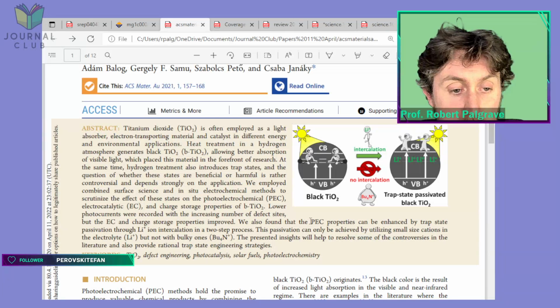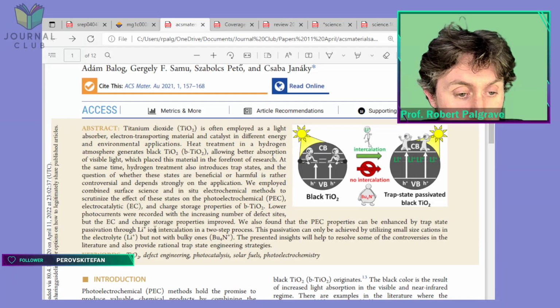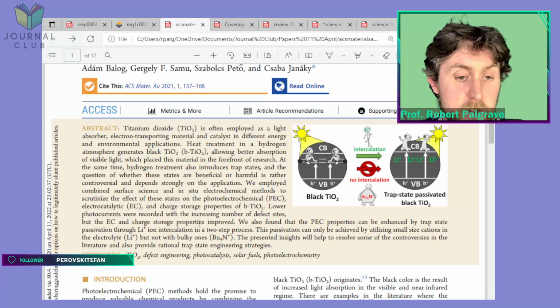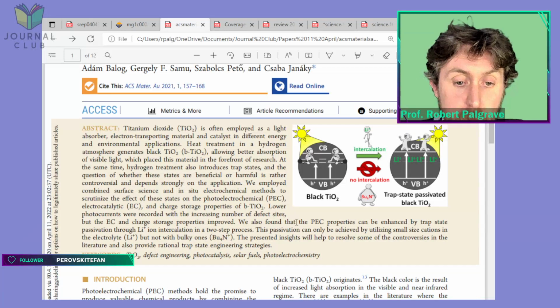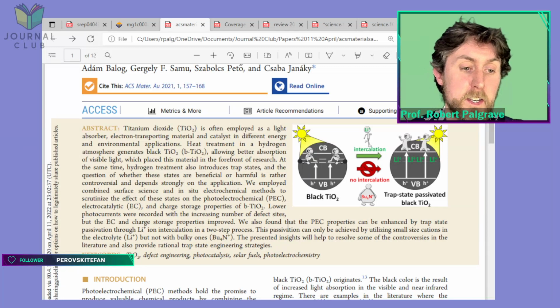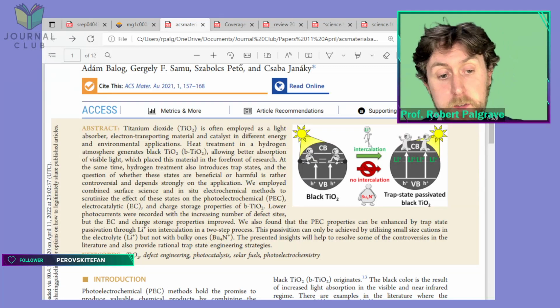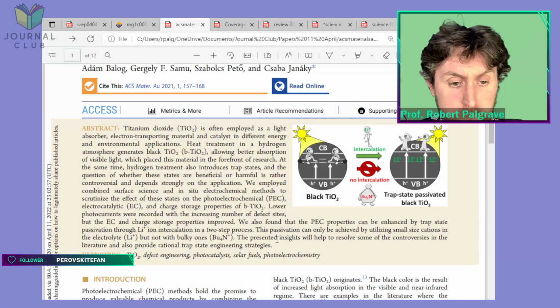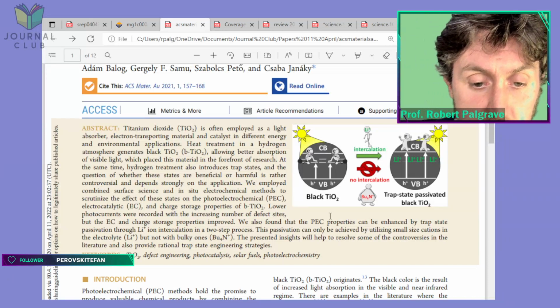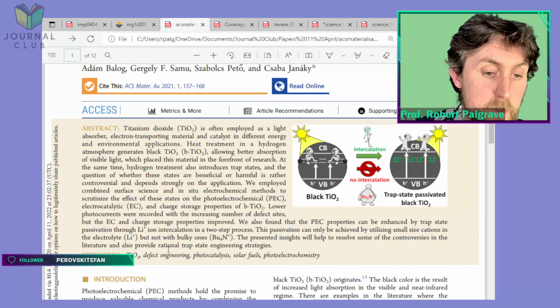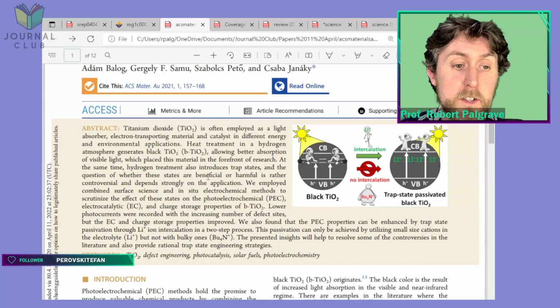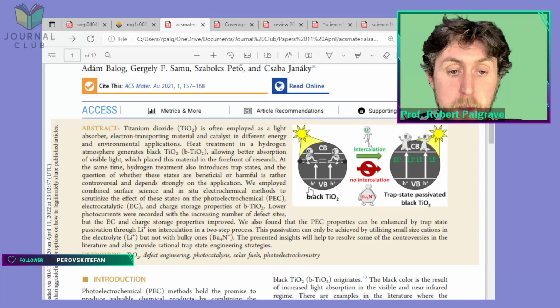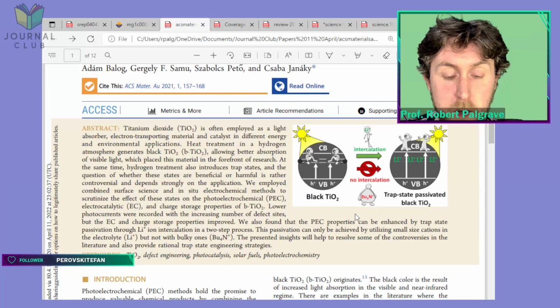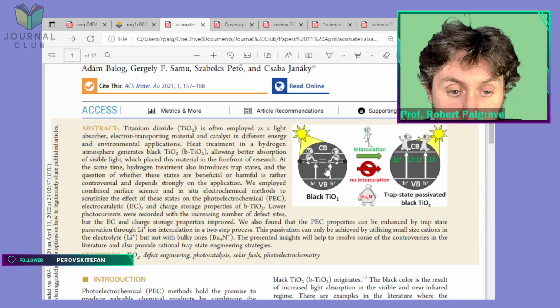We also found that PEC, photoelectrochemical properties, can be enhanced by trap state passivation through lithium-ion intercalation in a two-step process. The passivation can only be achieved by utilising small-sized cations in the electrolyte, but not with bulky ones, tetrabutylammonium. This thing here is tetrabutylammonium. The presented insights will help to resolve some of the controversies in the literature and also provide rational trap state engineering strategies. Okay, so nice abstract there. I think they kind of clearly sell out what they want to do, but maybe even more so is, of course, the graphical abstract, which shows a nice little cartoon here.